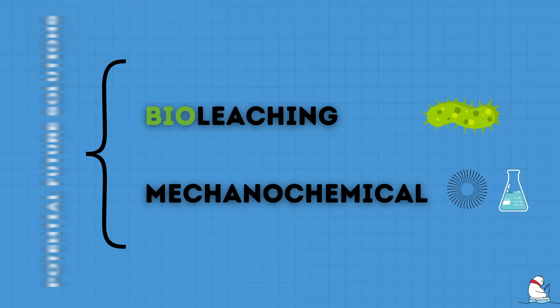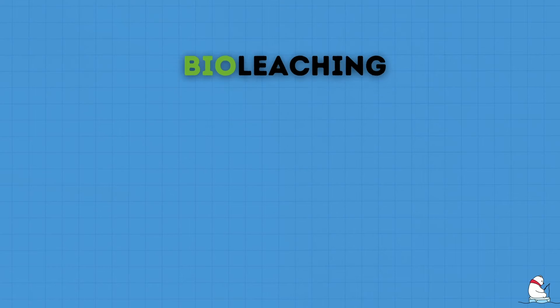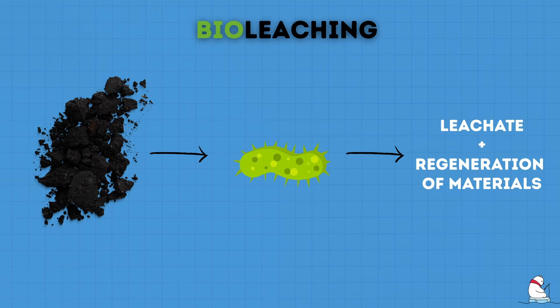New approaches or improvements to current methods, either at the pre-treatment stage or later, include the mechanochemical approach using ball milling, and bioleaching. Bioleaching, also known as biohydrometallurgy, is a recovery of metals using microorganisms. When added to the black mass, these microorganisms act as a catalyst — they produce acids which convert insoluble metals into soluble metals in an extractable form. Since lithium bioleaching involves living microorganisms that are hugely dependent on specific conditions, the parameters of this process need to be tightly controlled to ensure they can both grow and leach lithium.